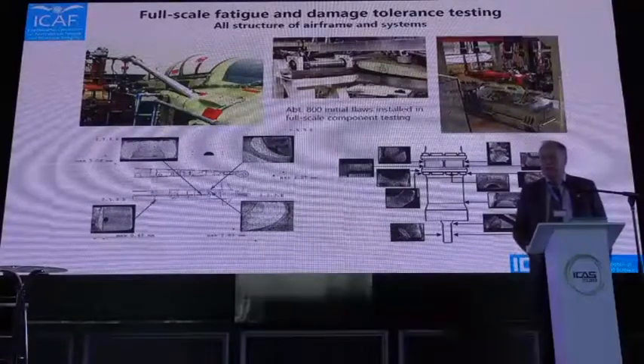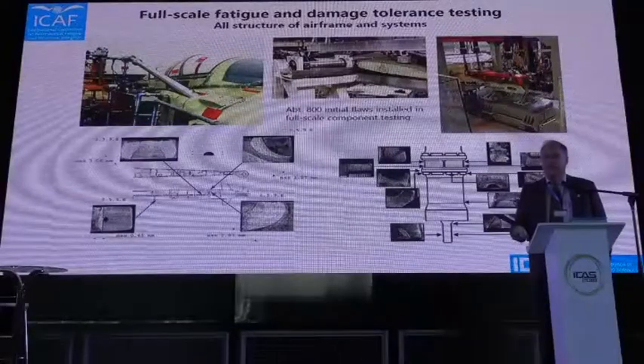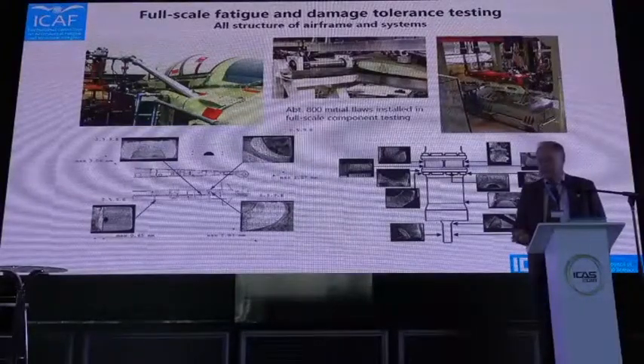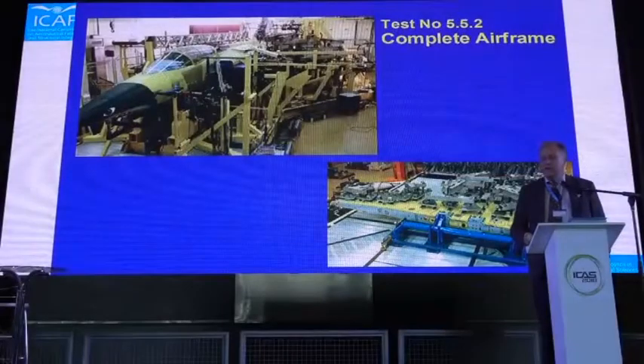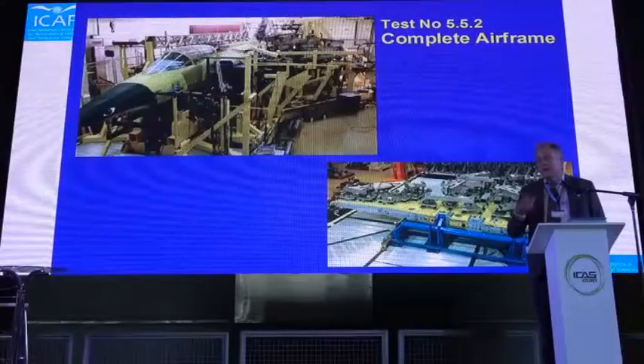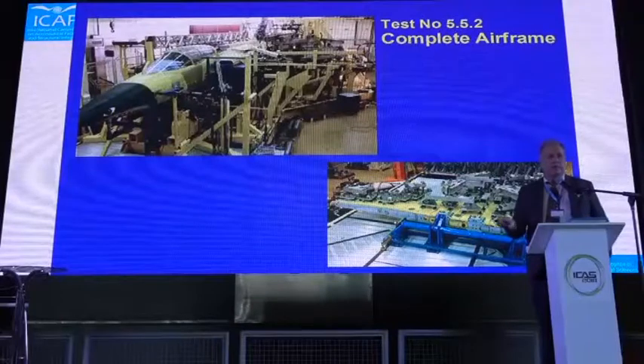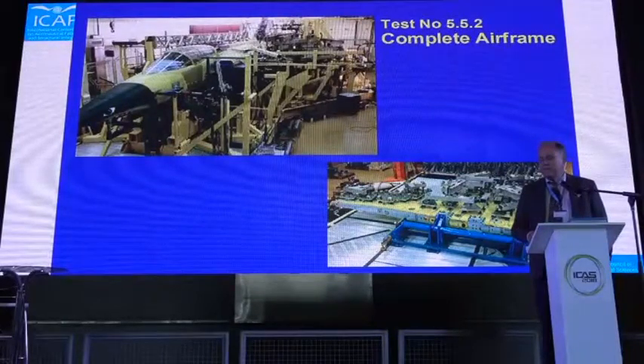This shows work in Sweden for the Gripen aircraft, where you see that about 800 initial flaws were installed in critical locations, and a full-scale test can look like this, typically with 120, 140 load actuators. Goes on for many, many years, and you always want this test to be far ahead of the fleet leader out in service, such that we will discover any possible new mechanisms occurring due to design changes or new materials.